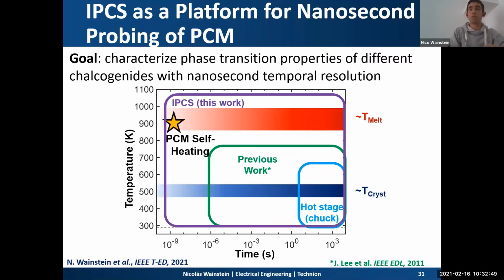So in this work, we used the IPCS not as an RF switch. I want to emphasize that, not as an RF switch, but as a platform for nanosecond probing of the PCM and other materials in the future. This is due to the intrinsic decoupling that exists between the actuation path and the PCM because of the isolation layer. With the IPCS we can also probe the melt-quench process, which was not possible with previous works. And this platform can help us understand the fundamental material properties of PCMs, particularly the physics of the melt-quench process in nanoscale devices. We can also use it for interface versus bulk effects measurements, and drift and threshold voltage phenomena characterization.